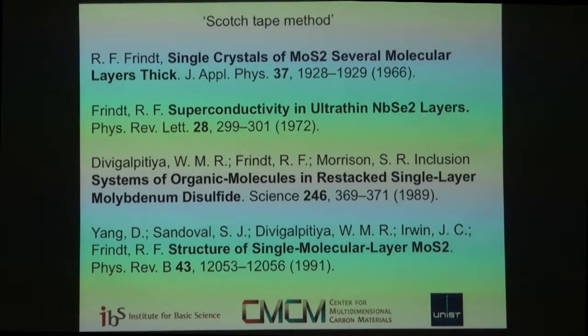So it particularly has been useful with graphite itself for making ultra-thin support films for TEM. So the breakthrough at Manchester was to find the route to getting monolayer insulating substrates, which was very important. But there is this sort of fascinating history, including making probably down to maybe 5 or 6 layers thick, but being a transmission electron microscopist and not a solid-state physicist, and that's a fantastic support film for TEM studies.